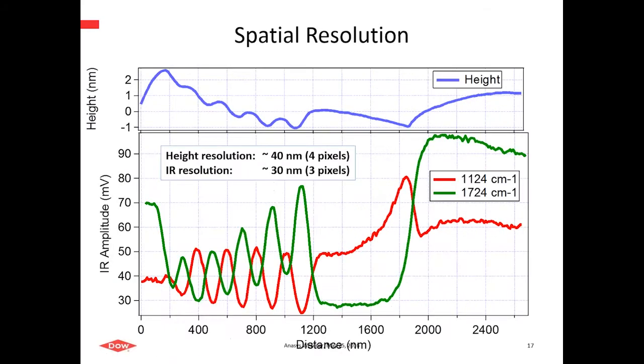And we can do more than that if we can overlay them to see, in fact, that they are out of phase, one with the other, and make our resolution estimates in this case. These were taken at higher pixel resolution, and now we are able to see about 30 nanometer spatial resolution from the spectral mapping. The other thing that gets us excited about something like this is that those of you who are more familiar with conventional surface analysis might more conventionally go after studying this kind of stack using, starting from the outside or left side in this case, and working in, a sputter experiment, sputter depth profiling, and track using XPS or SIMS, X-ray photoelectron spectroscopy, or secondary ion mass spectrometry to track these compositions. But we see it here directly in the morphology.